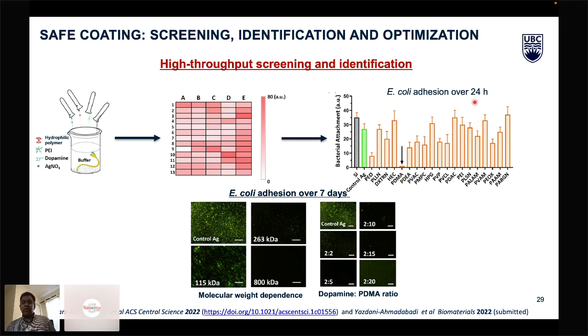The screening was done for 24 hours, and then we further extended the screening to 7 days. What we found is that the molecular weight as well as the composition of these coatings are really important in generating a coating with long-term activity. So our criteria for generating this coating was to extend the screening process over 7 days, because we want to make sure that this surface coating has long-term activity.